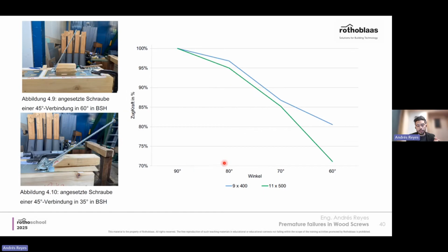Depending on the angle, 90 degrees would be the perfect angle of inclination, and this is 10 degrees of misalignment, 20 and 30. So you see how the performance changes from 100% to 70%, depending on the installation. Of course, 60 degrees is a lot. I really expected it to be more impactful, but we're talking here about dry conditions. So we know from this, okay, improper installation can have a permanent effect on the dry performance of fasteners.